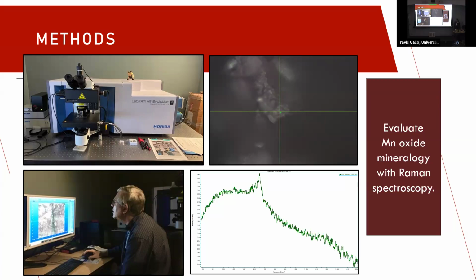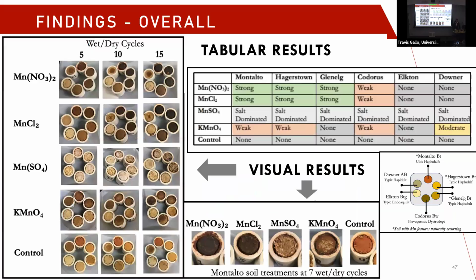It gives a mineralogical fingerprint of the mineralogical makeup of the sample, and Raman spectroscopy is uniquely suited for manganese oxides because the laser beam is being absorbed by the entire black color of the sample, and so you're just getting back exactly what you want, especially since coatings tend to be very thin, and you're not getting any noise in the data from underlying clays below.